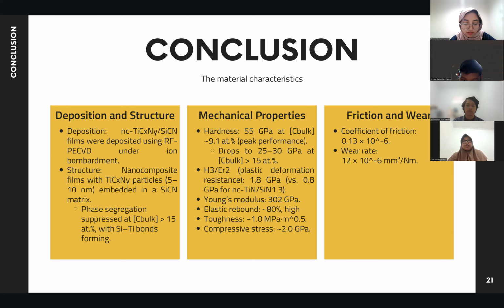For the mechanical properties section, the hardness level is 55 GPa at around 9.1% for peak performance, and it drops to 25 to 30 GPa at more than 15%. For the H3 or ER2 as plastic deformation resistance, it is 1.8 GPa versus 0.8 GPa for the titanium nitride, or silicon nitride 1.3. For the Young's modulus value, it's 302 GPa. The elastic rebound is around 80% high. The toughness is 1.0 MPa, and the compressive stress is around 2 GPa.